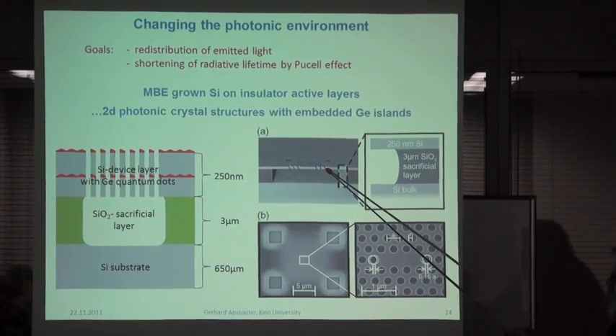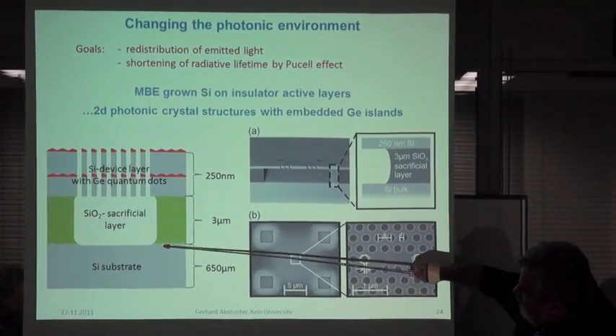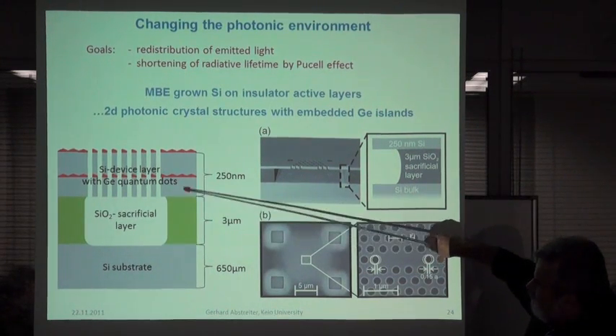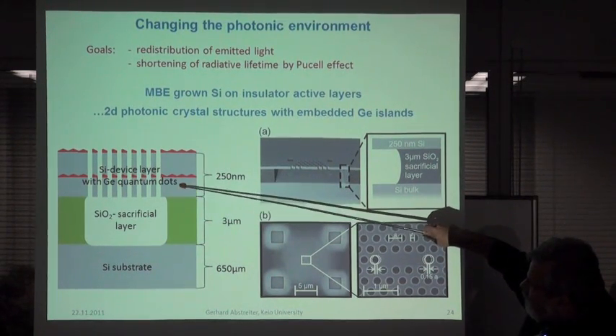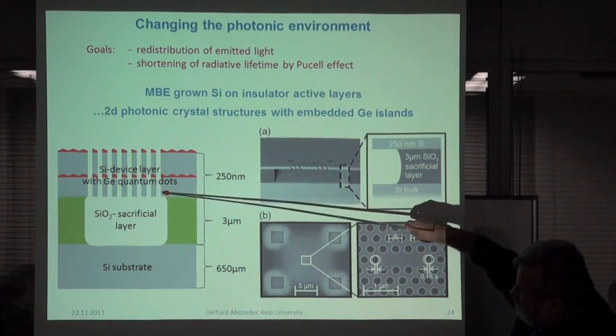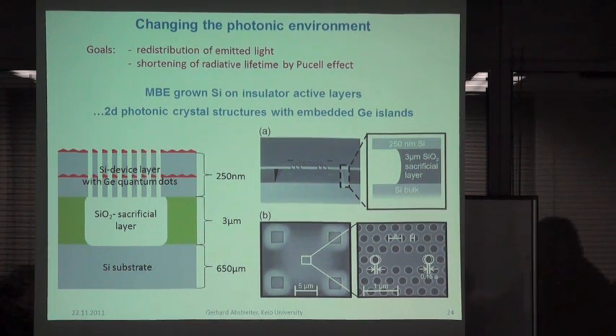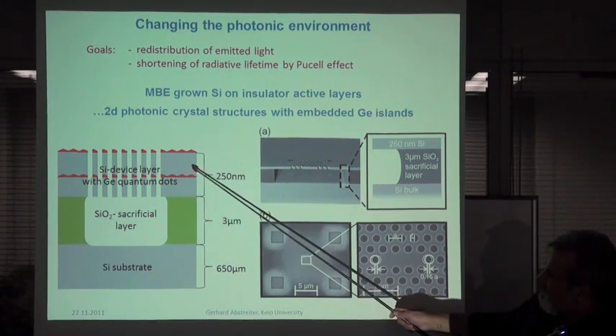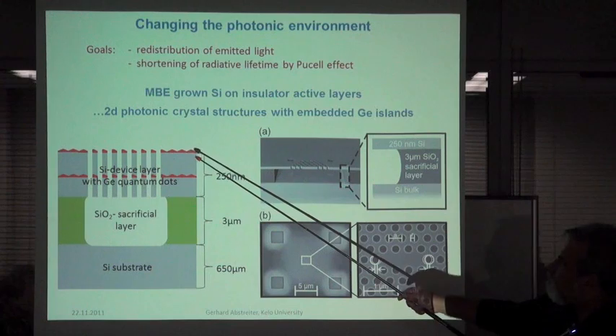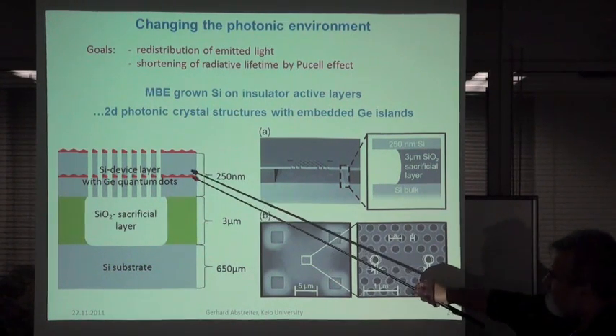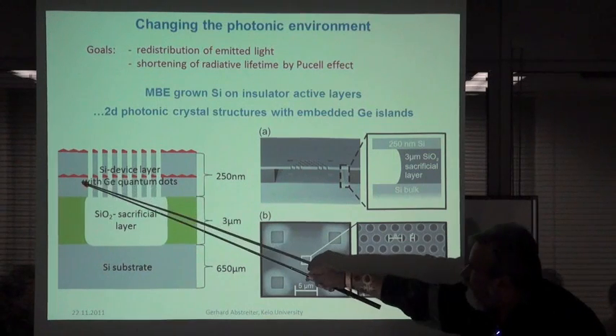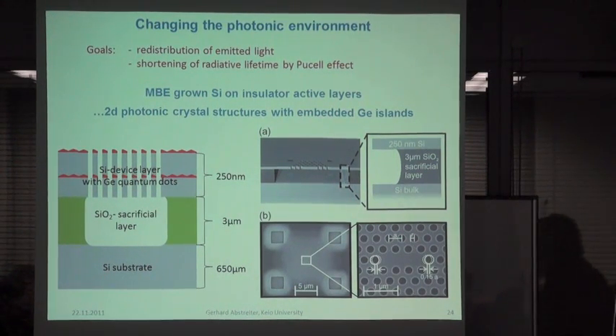membranes which we make as photonic crystals, it's two-dimensional, is basically a silicon on insulator. We have a silicon substrate, silicon dioxide, and then silicon actually epitaxially grown, with the top silicon layer thinned down to something like 20 to 30 nanometers, and then we grow with MBE and have an active layer in here. And if I want to see what the dots are, I can also have one on the top under similar growth conditions. But for the active samples, we use only the sample in between. And then we can fabricate with e-beam lithography holes into such a membrane, underetch the silicon dioxide, and then you have a two-dimensional photonic crystal here.